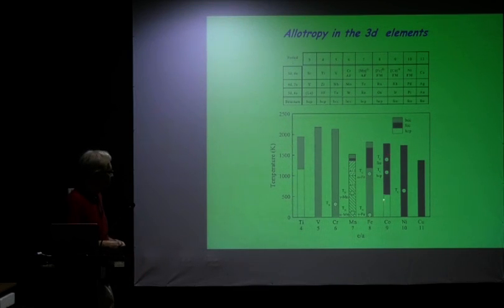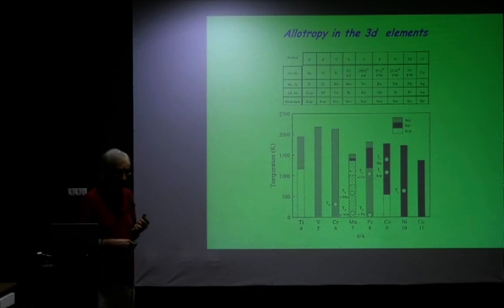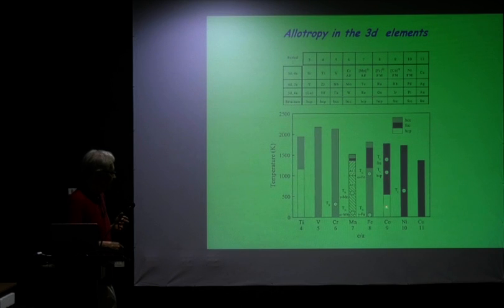Still, when you come to cobalt, cobalt is hexagonal at low temperatures. When you go to high temperature, it becomes face-centered cubic. You can measure a Curie temperature of the face-centered cubic phase, which is up here, and it's quite high. You cannot measure directly the Curie temperature of the hexagonal state because before reaching a Curie temperature, the structure changes and you come into the FCC state. Of course, then you have nickel, which is stable everywhere with a Curie temperature around 600 Kelvin, and then you have copper, which is not magnetic. So this is how this structure varies all throughout.